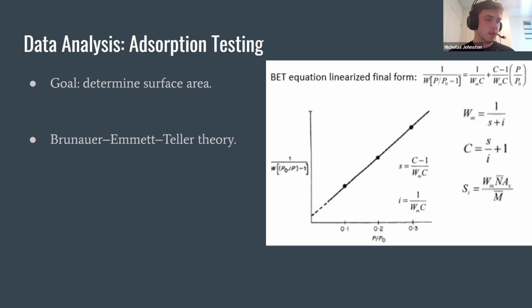Next slide, please. The next thing that we'll use to analyze our samples is adsorption testing. And the goal of that is to determine the surface area, which is one of the main areas of our research. It can tell us the surface areas for particles that have pores of many different sizes. There's 3 different categories of pore sizes. I think it's micro, meso, and macro, where microporous has a pore diameter of less than 2 nanometers. Meso is 2 to 50 nanometers, and then macro, I think, is greater than 50 nanometers. That's the diameters of the pores of that material. And I think we'll get into that a bit later.